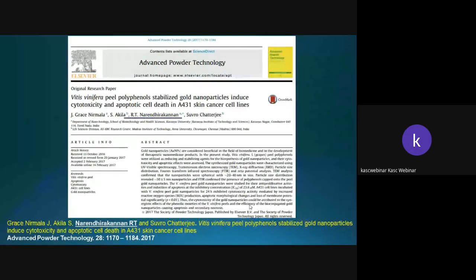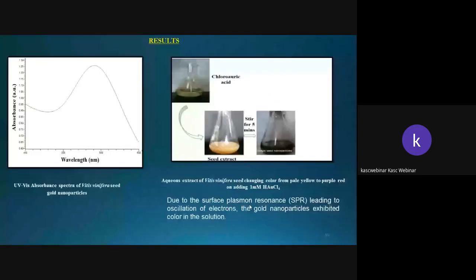So this is one of our publications, which was done with Anna University, Chennai. So in this, you can see that after addition of Vitis vinifera peel extract to the chloroauric acid solution, within 10 minutes a change of color of the solution from yellow to purple was noted, signifying the formation of gold nanoparticles. It was confirmed by UV visible spectra analysis showing the plasmon wavelength around 540 nanometers. And a rapid increase in the synthesis of nanoparticles was observed with an increase in reaction time, due to surface plasmon resonance leading to oscillation of electrons, so the gold nanoparticles exhibited color in the solution.